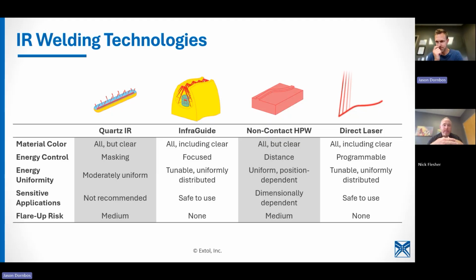We found that the key to processing is matching the absorption of the energy at the surface of the part to the ability of the plastic to conduct the energy into as deep as you want it to go. So that's sort of language that we use here from a process standpoint. You want to get that energy in. If you just melt the top and you have to push everything together, all of your good semi-molten material is gone.